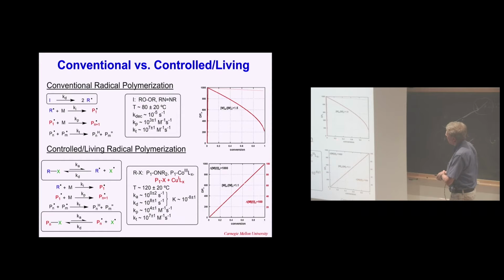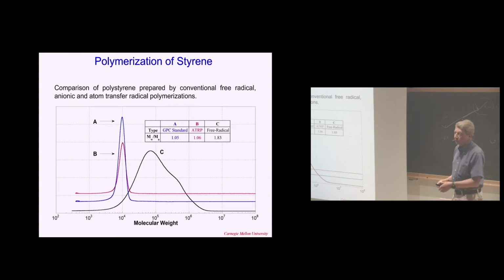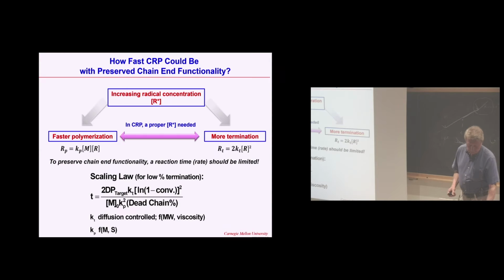You remember this high molecular weight at the very beginning in a second, and then dropping down with conversion, high dispersity. And here all chains grow concurrently with conversion, having very low molecular weight distribution and very high uniformity. So if you inject these samples on GPC, this is a GPC standard, this is ATRP-made polymer, and this is conventional free radical polymerization. So very, very different.